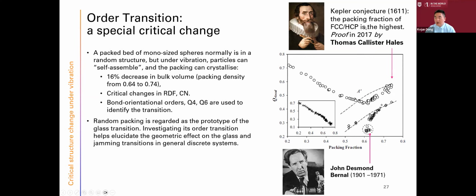So that's really a conjecture that has a long history back to the 17th century, but just got proved in 2017. And people understand this can be proved that this is really the highest packing fraction, which is also the most ordered packing. But here is the random close packing point, which is a glass transition point. So although the structure model has been linked with the glass transition, people still do not understand why we need such critical change, why the normal packing will just stop here, will not go up to here.